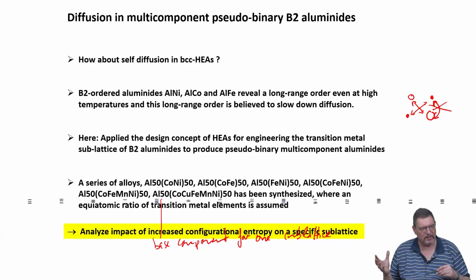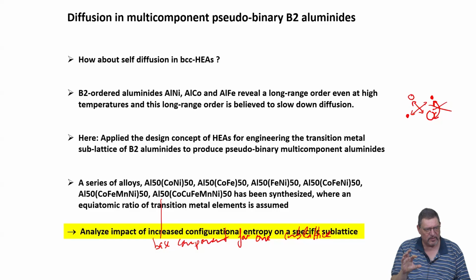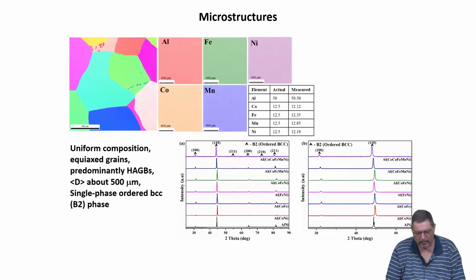So with two sublattices, we're only changing one. The aluminum sublattice is staying constant, and the other sublattice is then going from a binary to a high entropy system. Again, we have or can achieve uniform compositions, equiaxed grains, large grain size. We have in the material mostly high angle grain boundaries, and as you look from the X-ray, single phase ordered BCC.